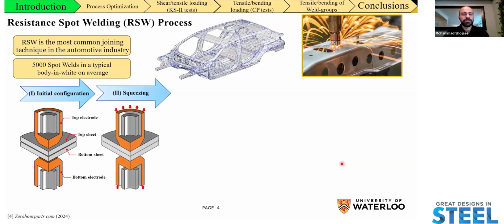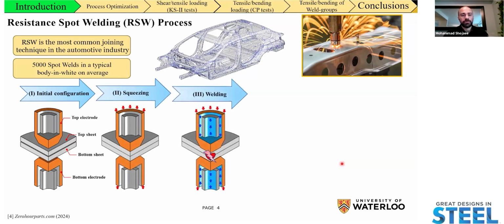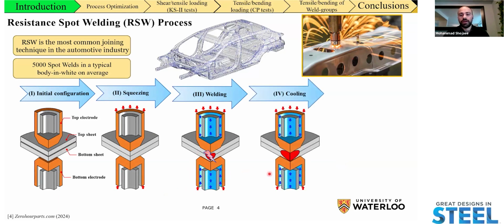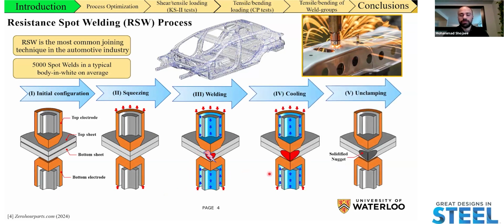And upon establishing a predetermined amount of force and welding current, we get localized heating at the interface between the two sheets where we have the highest resistivity. And upon melting and cooling, we get a solidified joint in between the two sheets.